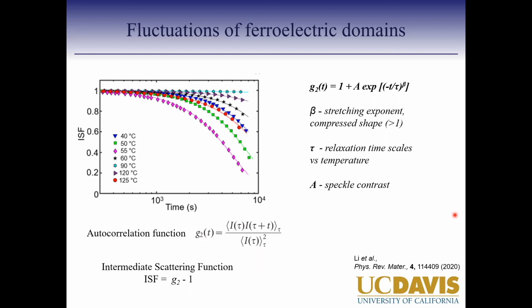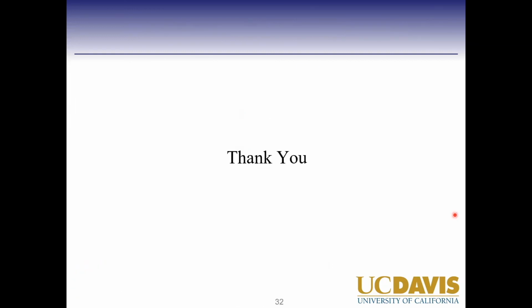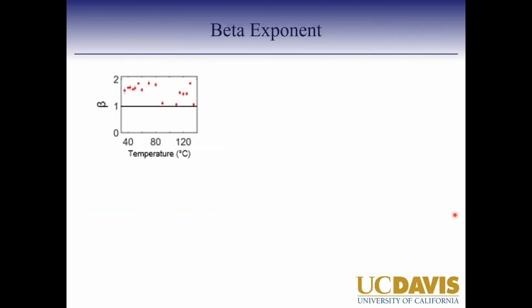Sorry, I was just following up on that. Is A constant as a function of temperature, and beta as well? Let me see if I have A as a function of temperature. Oh, I don't have A. So this is the beta which we measured as a function of temperature. For most of the temperature range, it's 1.5. Where we were really static, where nothing was happening, that's where it fit 1, which doesn't mean much. And this is a point which we are measuring again, because we didn't have enough photons at this higher temperature because the intensity was so small. So I don't trust it yet.